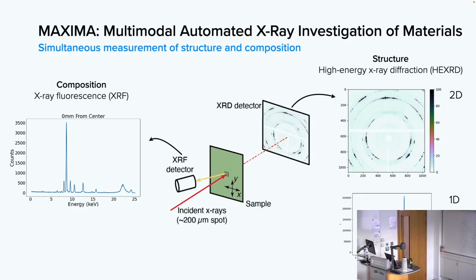As I mentioned, the distribution of intensity around these rings tells you something about the crystallographic texture. If you want to do phase identification, of course, it's easier to then integrate around those rings to get a one-dimensional diffraction pattern, and now you can do your standard phase identification routines. As long as we have an X-ray beam shining on the sample, we're going to get fluorescent X-rays out, so we might as well stick an X-ray fluorescence detector there and allow us to measure composition, which is helpful if we have one of these compositionally graded samples.